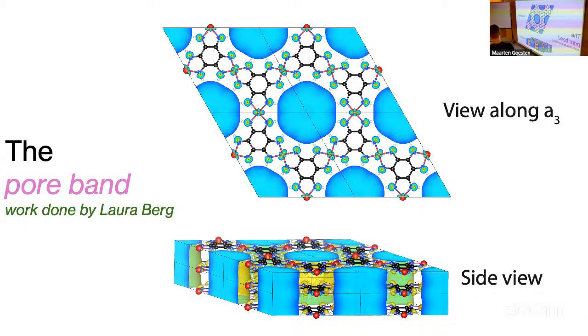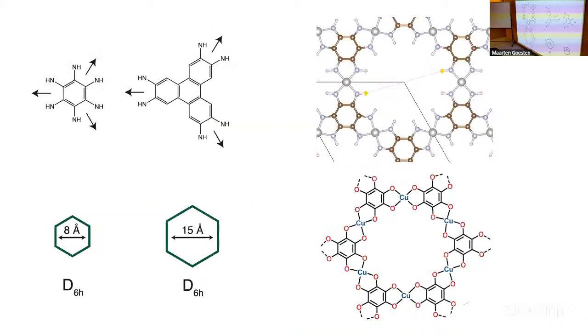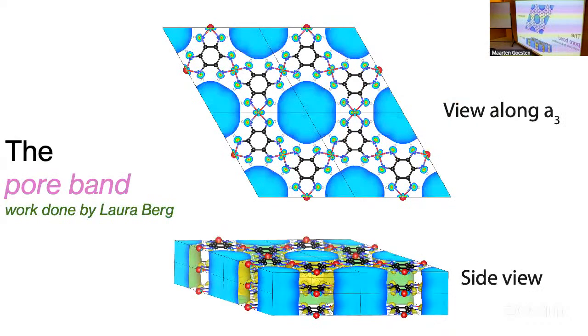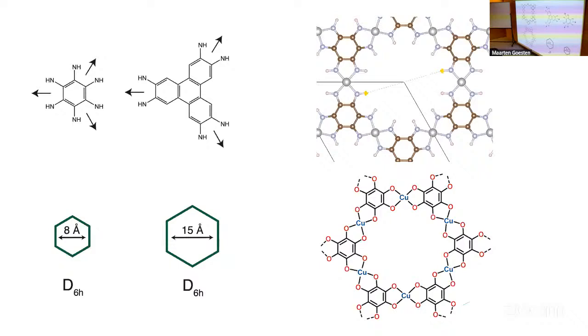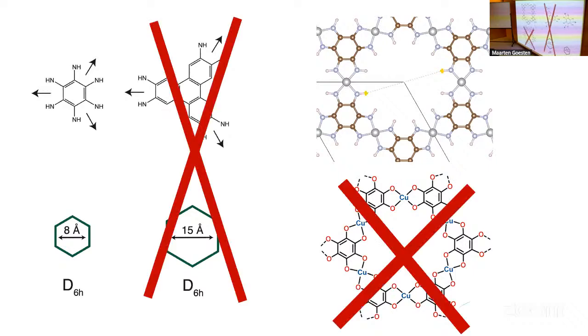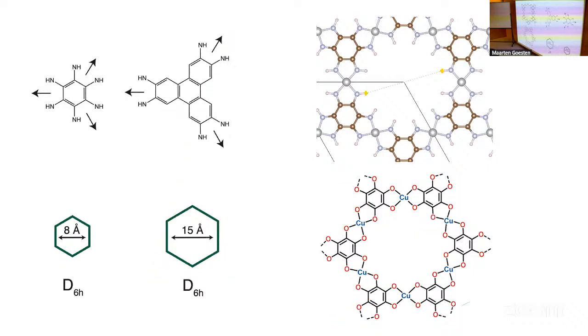What we see here is a band where the electron resides in the center of the pore. Crystallographically, it is the Wyckoff 1a position. Because this is behaving like a free electron, you can also recognize it by calculating the representations, because it will always transform +1, so totally symmetric, under all the operations of the point group. This is work done by an undergraduate student who has done amazing work. These are very preliminary images, but we see, for instance, that if we move to larger MOFs, to this isoreticular system, which is larger than this one, we don't find this pore band.